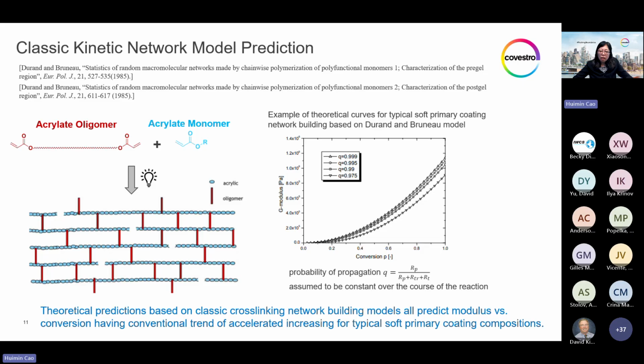And with classic kinetic network model prediction based on the statistics of how each type of free radical reacts, the monofunctional monomers build the backbone and only difunctional oligomers build the crosslinks. And only when both sides of the oligomer have reacted, one complete crosslink is built, leading to a small rise of the crosslink density and therefore a small modulus increase, right?